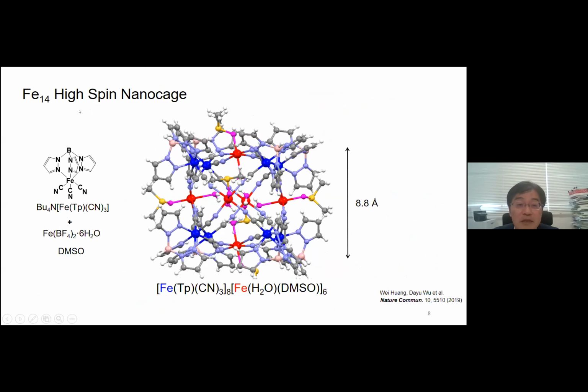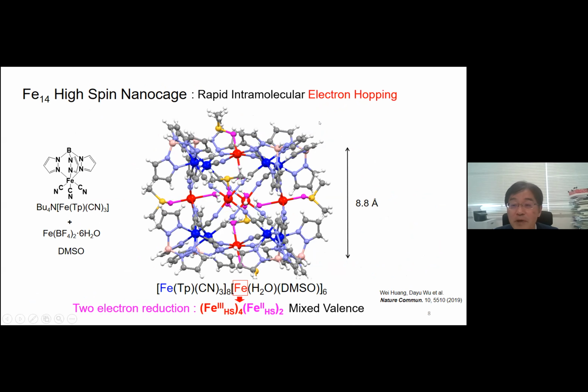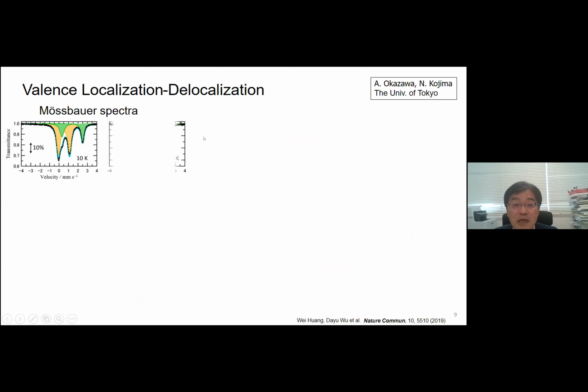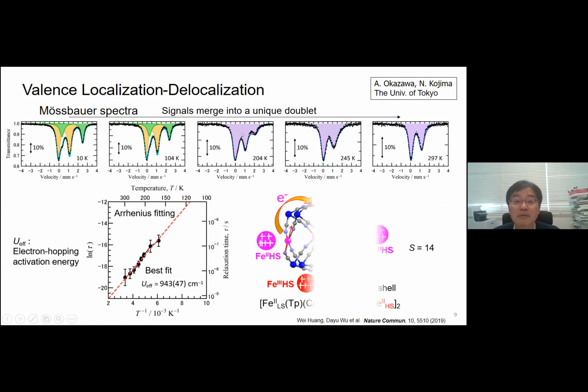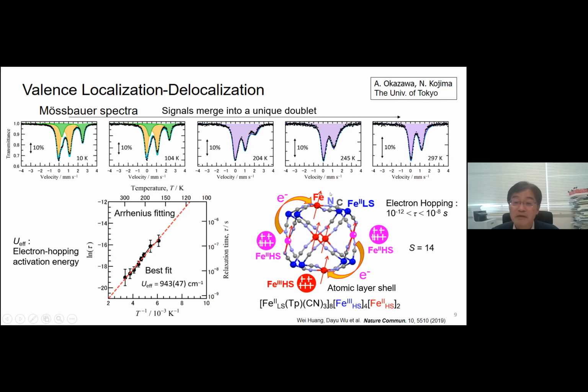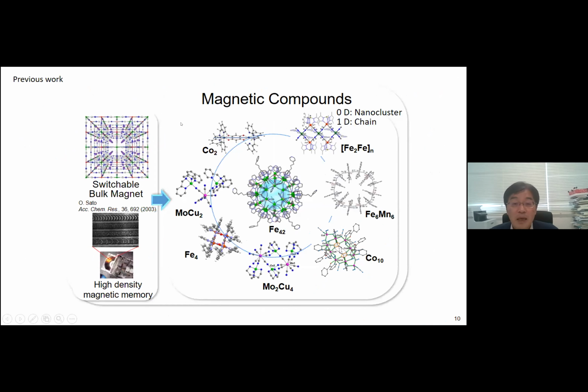And furthermore, we reported this new high-spin nanocage compound. And importantly, this iron site is partially reduced. So this is mixed valence state. So this molecule exhibits rapid intramolecular electron hopping. This is confirmed by Mössbauer spectroscopy, as shown here. These two signals merge into a unique doublet. So this means electron hop around this atomic layer shell, and the hopping rate is faster than the Mössbauer time scale, 10⁻⁸ seconds. And we reported several other magnetic compounds.